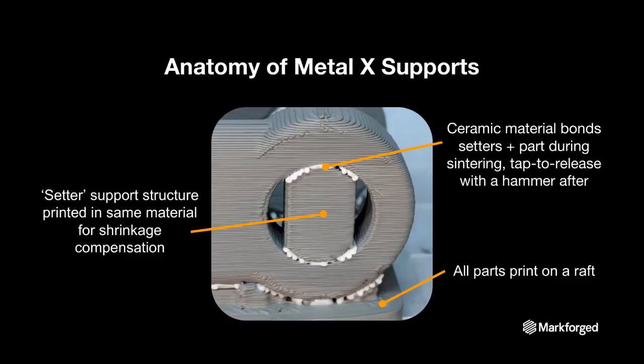So as everything is starting to shrink down during that sintering process, you want everything to shrink really nice and uniformly and gently. If you had materials that shrank at different rates, this would become a problem, and you'd be running into more issues. So what we do is we print this setter structure that holds everything into place in the same material while it's sintering. Now, the other thing is you don't want those support structures to bond to the part. You want to be able to take them out, or at least you don't want them to bond permanently to the part.